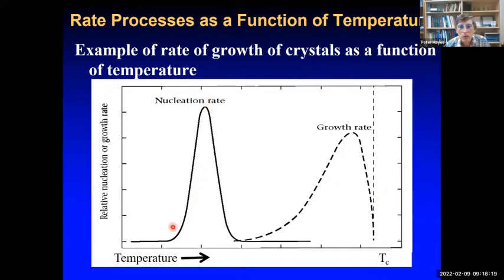So these are usually displaced from this critical temperature by quite a difference. So again, you can see if you're at low temperature, increasing the temperature will increase the nucleation rate. If you're at high temperature, increasing the temperature will decrease the nucleation rate. So not obvious.